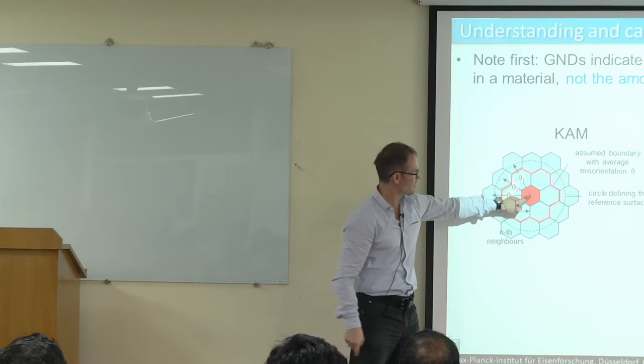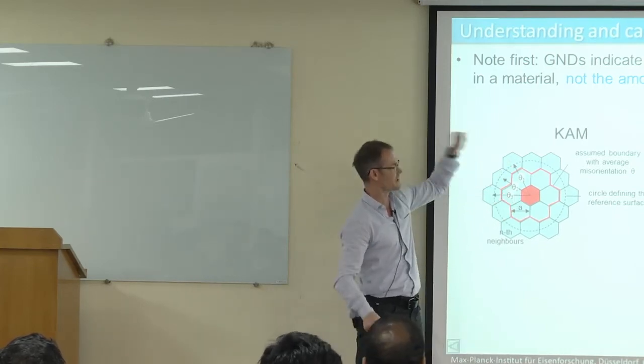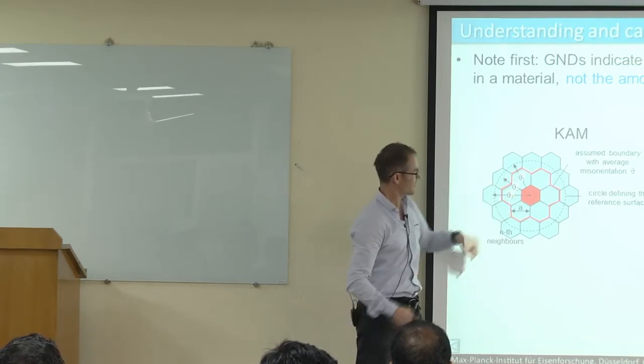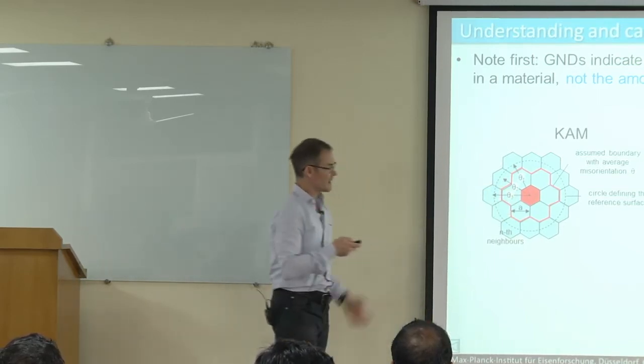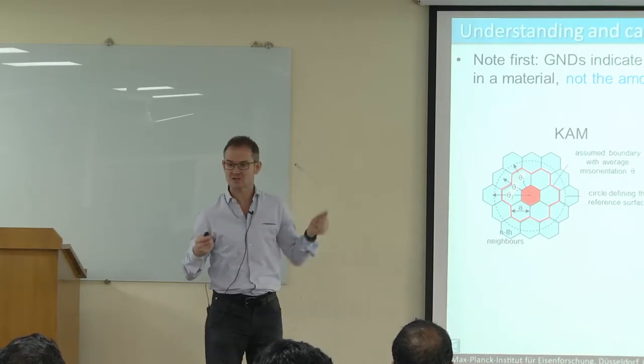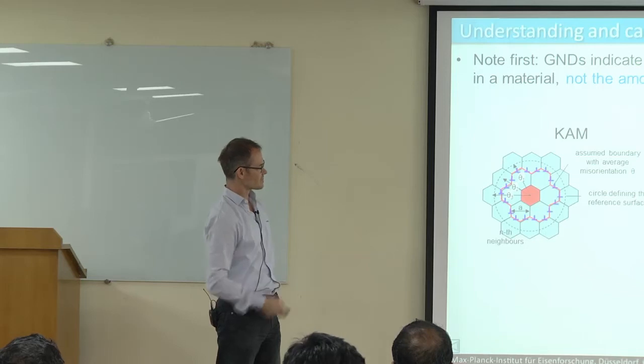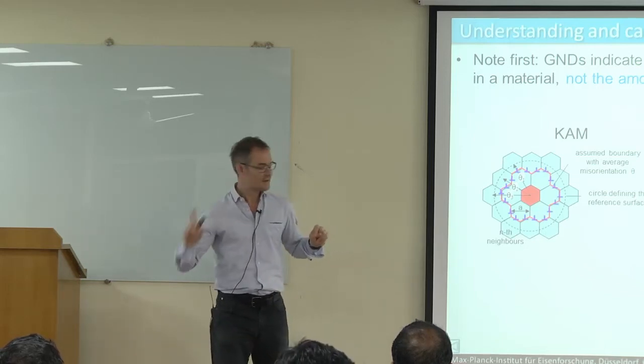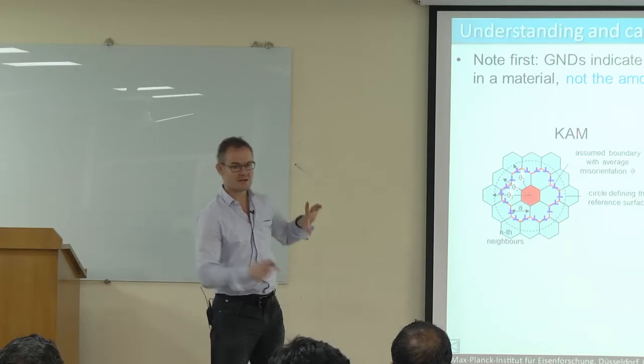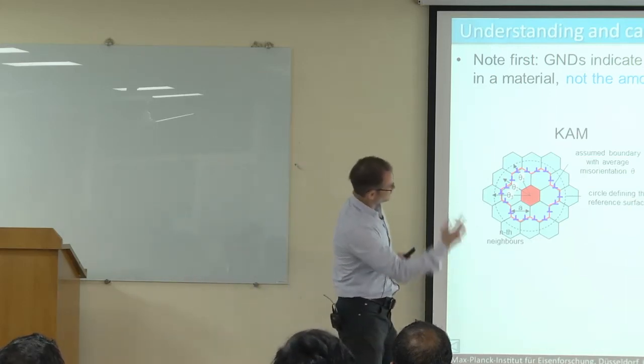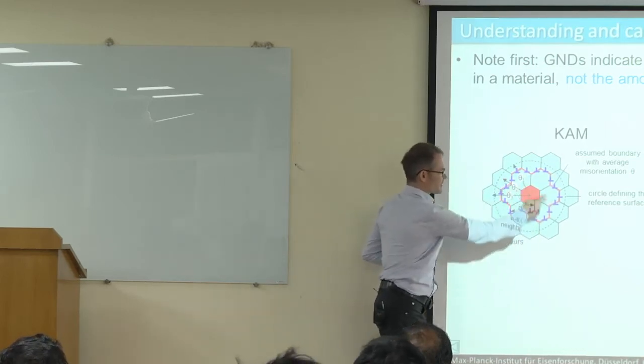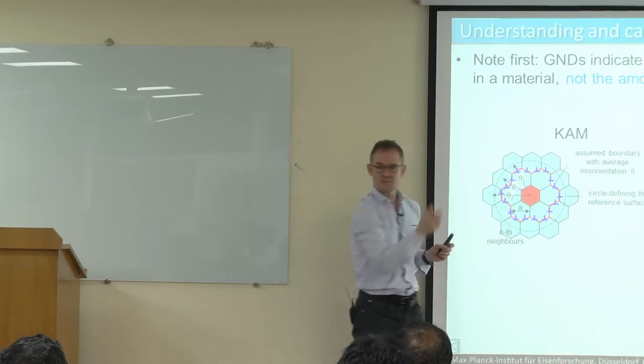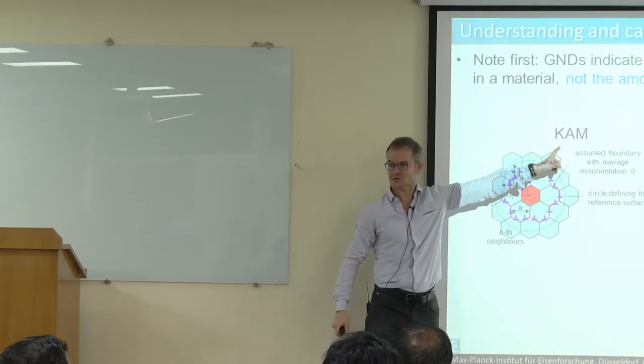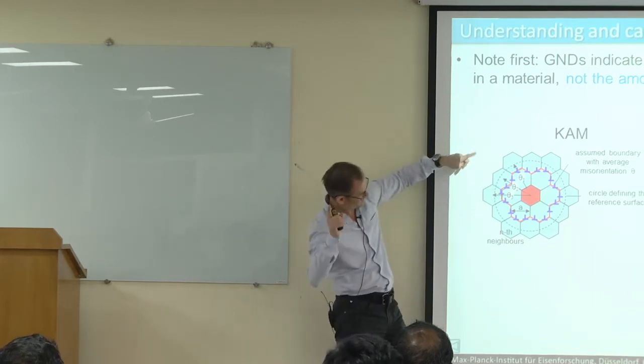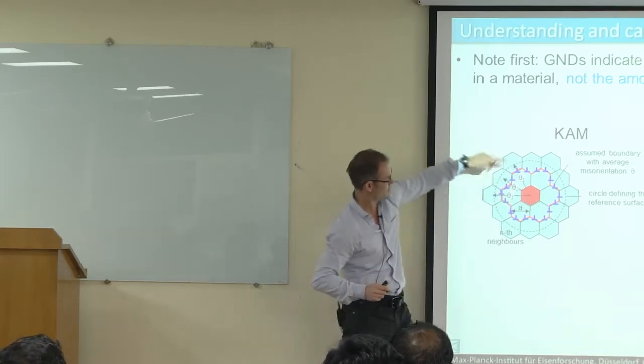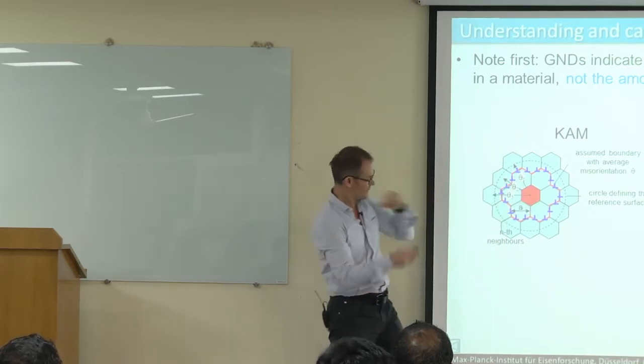And now I do the following. I take the center point and I calculate the misorientation between the center point and its surrounding neighbor, and of the next one, and then I average all of these misorientations, and I obtain a value which is called the average misorientation in this kernel, kernel average misorientation, KAM. Good. And now very nice is that I can quantify this KAM in terms of dislocations. I can say, okay, I assume that here's one grain outside, and inside is another grain, and between this inside and the outside grain, I have the misorientation exactly equal to the average misorientation, the KAM. And from this assumption, I can calculate how many dislocations do I need to create this rotation from one crystal to the other. And that's what I'm doing.